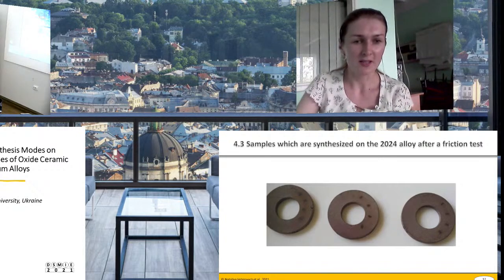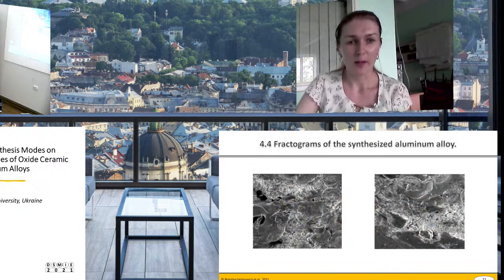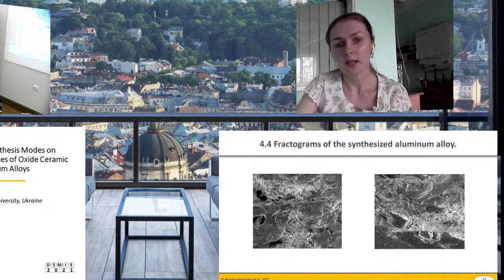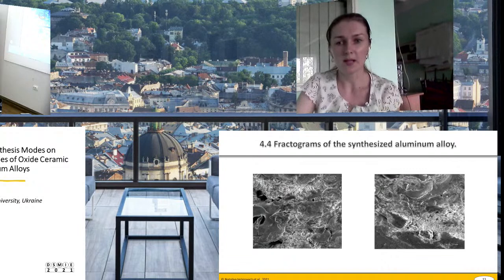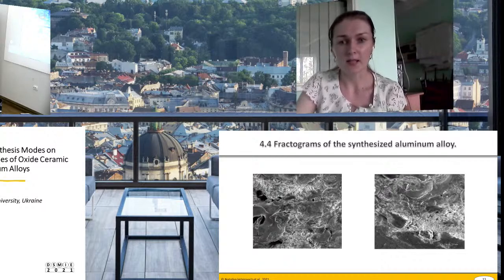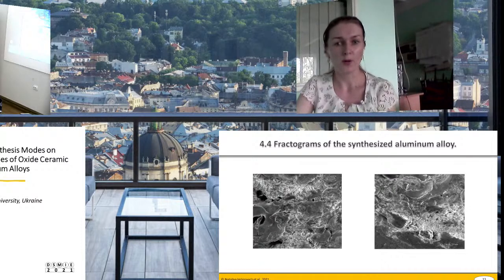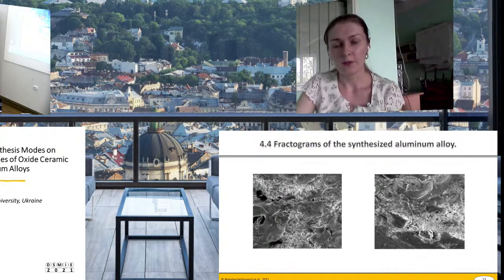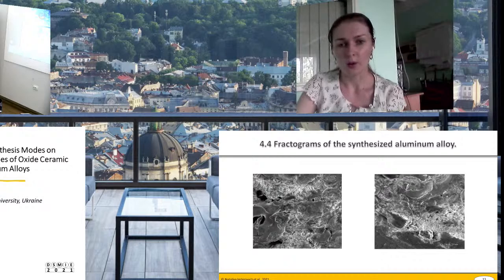Let's change the slide. If you are able to see poster 13, you can see that coatings synthesized by plasma electrolytic oxidation have low porosity. This is due to the fact that the coating is synthesized at high temperatures, which causes the pores to melt. The figure shows fractograms of the synthesized aluminum alloy.